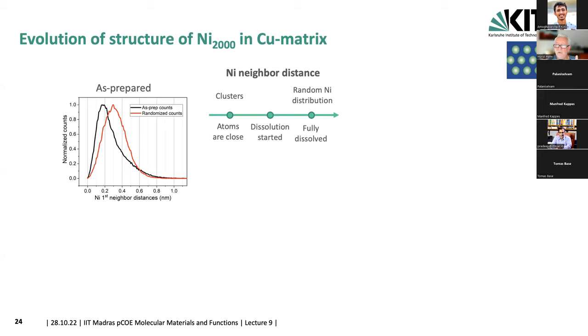So now, if you take the as-prepared material and you do the statistical counting in your APT measurement, you can get what is here as-prepared counts in the black curve on the left side. And you can compare that with the randomized counts, if you take all the nickel and randomly distribute it and you calculate what would be the statistical distribution, and that would be the randomized counts. And you see clearly in our measured sample, this is not randomized. And this corresponds to all that I showed you earlier.